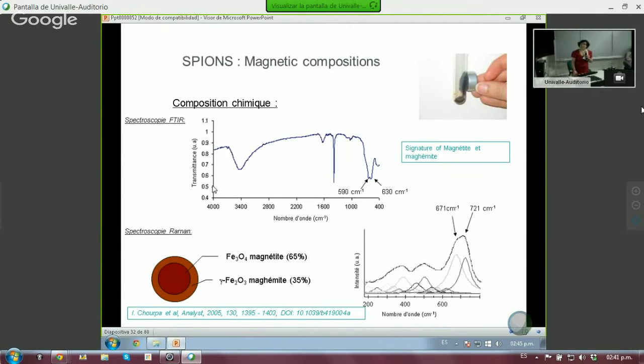So anyway, with this FTIR, you can see here that there are these two extra, I don't know if I can call them peaks, but they are more like minima. And this is a signature of the magnetite and the maghemite. And then we also did some Raman spectroscopy. And by fitting, we believe that these are the peaks corresponding to the maghemite and the magnetite. And then by fitting these, we were able to tell how much magnetite and how much maghemite we have. As you can see, it's essentially magnetite with about 35% of maghemite.